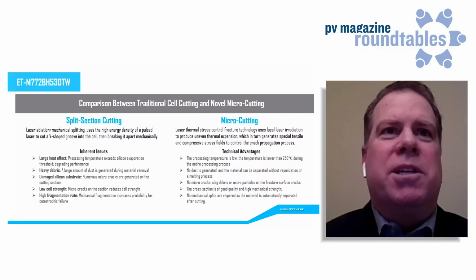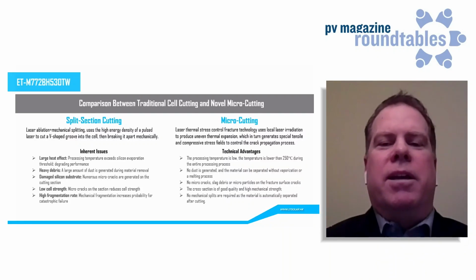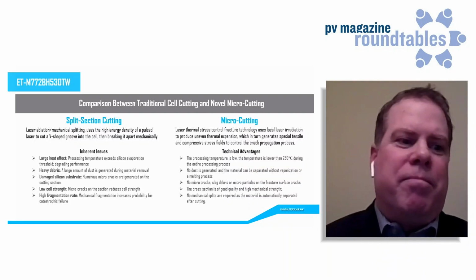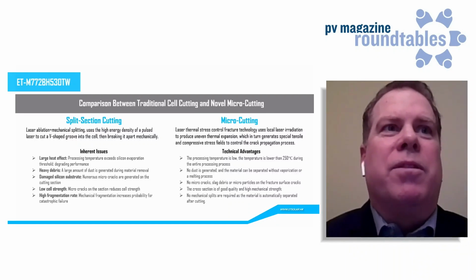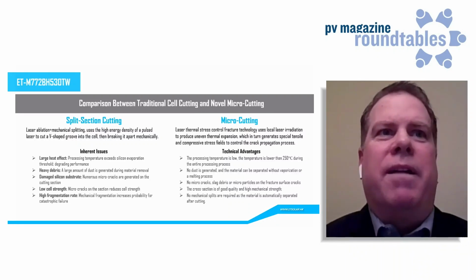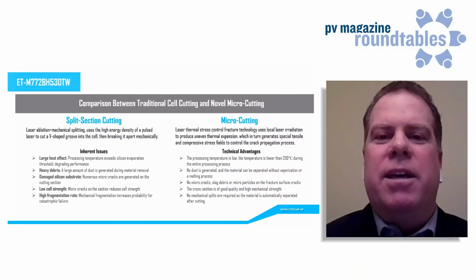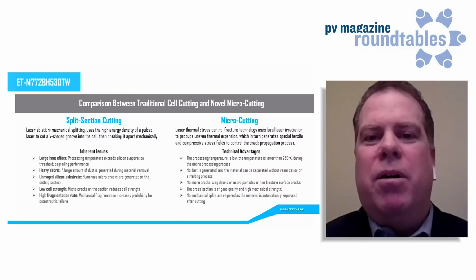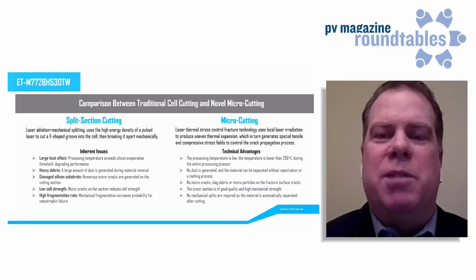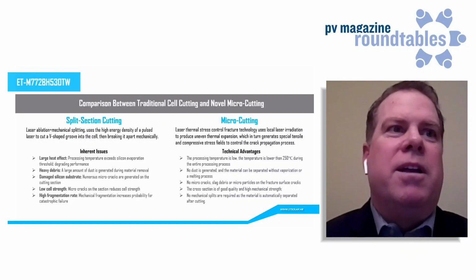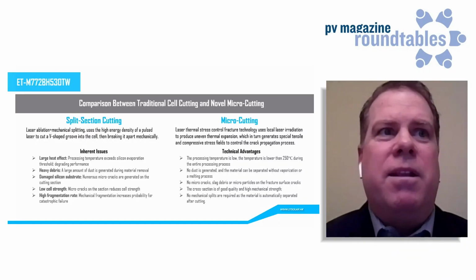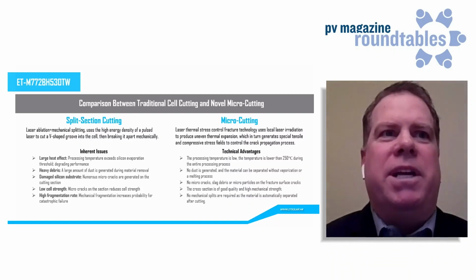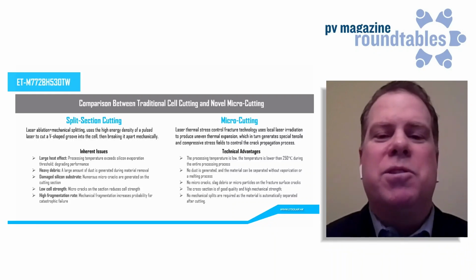So a typical split section cutting involves a laser ablation. So you're actually pounding away at the material with a high energy pulsed laser to cut a V-shaped groove into the cell. And then there's a mechanical split, a breaking apart of the cells. And this is the typical approach that's used in the industry. So there are some inherent issues with that, those being large heat effect area, which I showed in the previous slide. So the processing temperatures for those lasers exceeds the silicon evaporation threshold. So you get that damage to the material and a degraded performance.